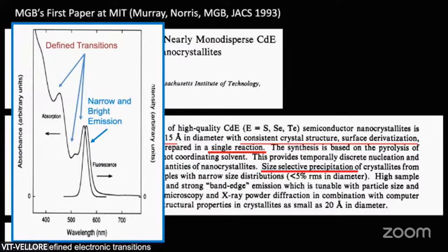It's like in music, it's the fundamental frequency of your flute or your string instrument. Then the other two peaks that are a little further in energy, and bluer in color, those you can think of as the harmonics of the system, right? So they're higher energy peaks that are harmonics of the fundamental. And then you have the emission peak, the one single peak, which comes straight out of the material, which depends on the size of the material.